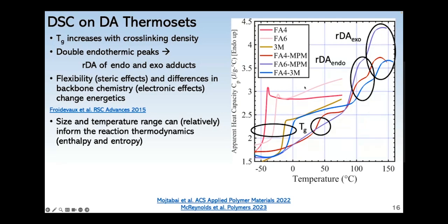And I'll first bring your attention to the step in heat capacity at low temperature, which is owing to the glass transition. And as you would expect, the Tg increases from the prepolymers to the full Diels-Alder thermosets from the cross-linking. In other words, it would take a higher temperature or more energy to make the polymer segments gain motion. And for the DA polymers at high temperatures, there are two endothermic peaks that occur because of the separate retro Diels-Alder reactions of the exo and endo adducts.